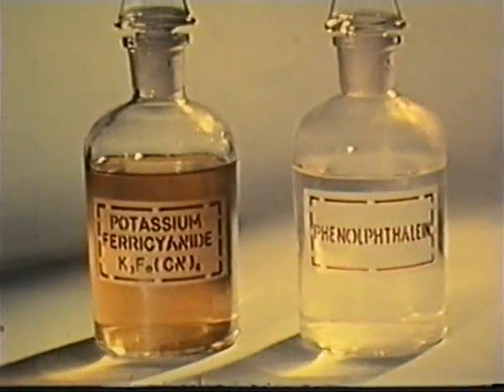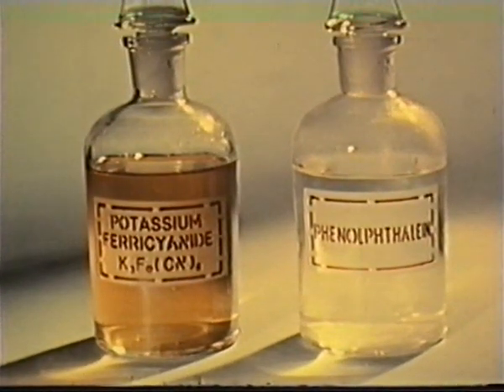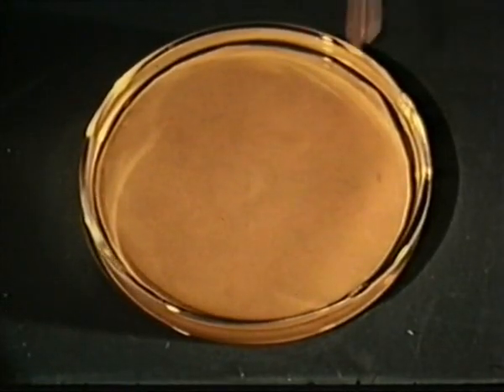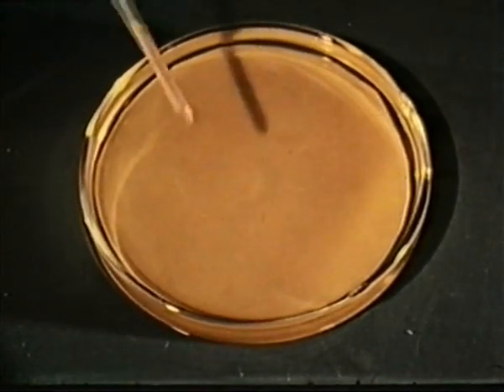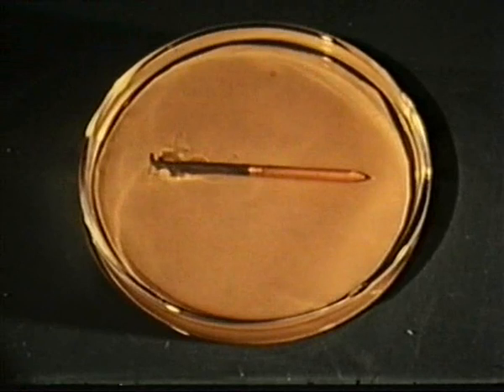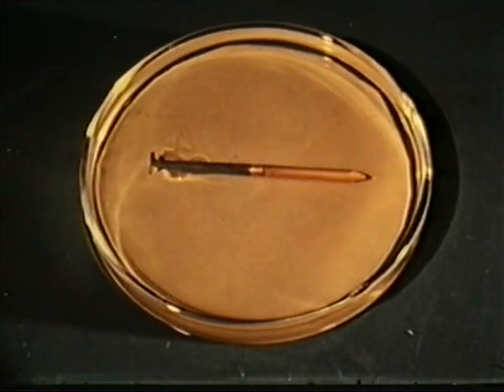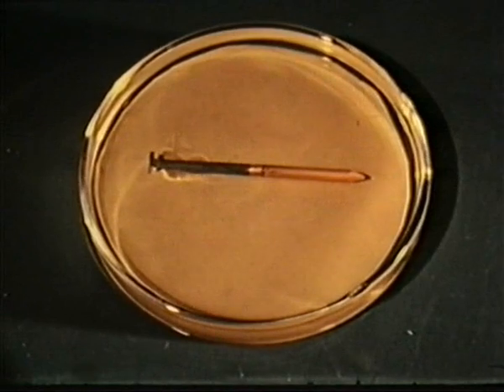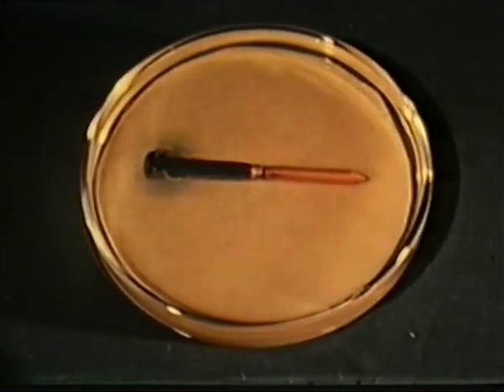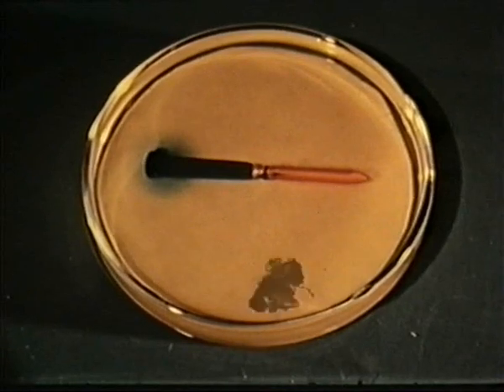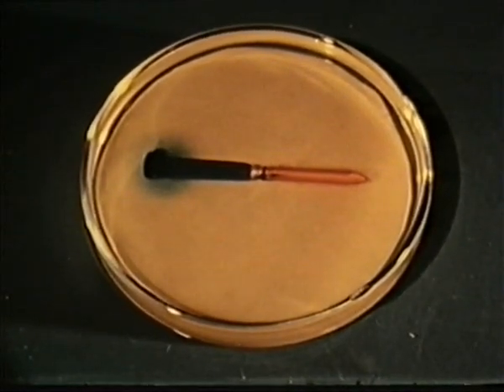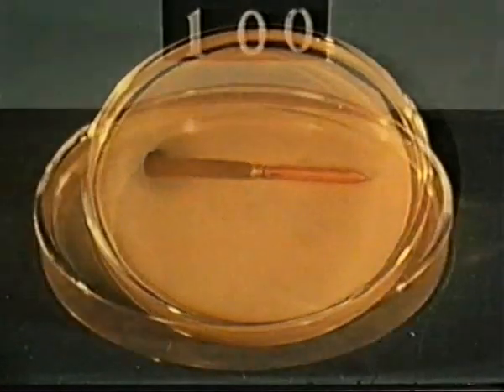The color-changing reagents used previously to demonstrate oxygen concentration cells can be used as well to show the existence and location of anodes and cathodes in other types of corrosion cells, such as those set up between dissimilar metals or from point to point on a single metal surface. For example, let us take an iron nail with copper plated on the pointed half of it. We will place this specimen in a gel containing sodium chloride, phenolphthalein, and potassium ferricyanide. As time passes, we will notice the development of a pink area around the copper-plated portion and a blue area around the bare iron half.